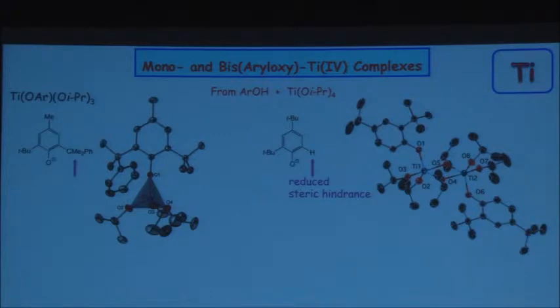So we started by looking at the monoaryloxy tris isopropoxide system. And we now compare two systems. This aryl group had the methyl group here, tertiobutyl here, and a rather bulky substituent in ortho position to the oxygen. And the compound you isolate is a titanium-4 compound, tetrahedral coordination geometry, what you would expect. Titanium-4 is usually tetrahedrally coordinated, and the 3 isopropoxide.